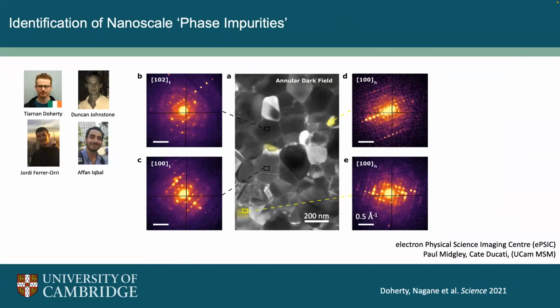What we find, just to tie up this section, is that these small nanoscale trap clusters are actually related to other phases, things that aren't perovskite. So we can look with very, very sensitive electron microscopy techniques, and most of these grains here are perovskite. We can index them. We can look at the crystal structure and find that they're perovskite. But these shaded yellow ones are actually other structures that are not perovskite and are problematic. And even though they're really tiny, they end up being quite problematic for the cell.